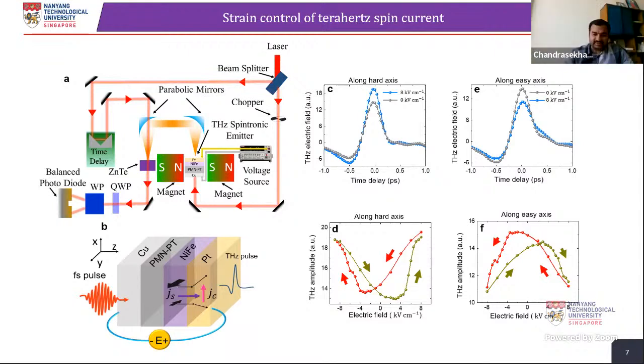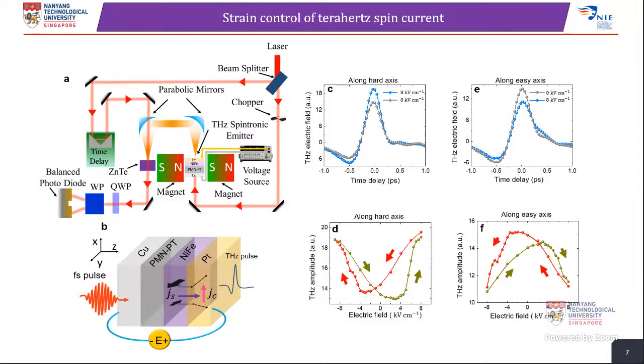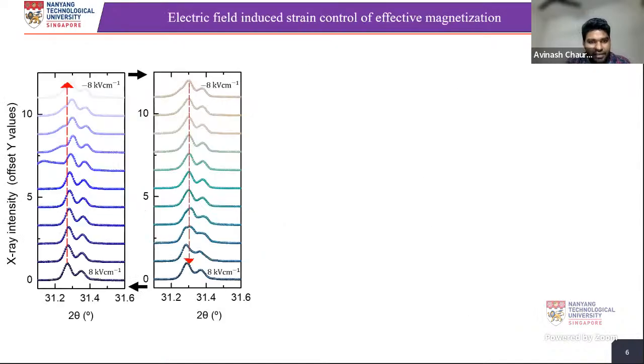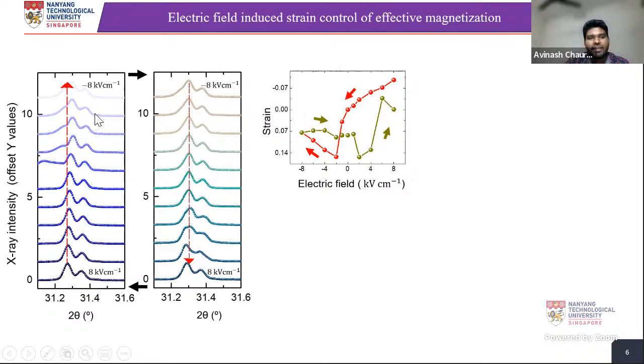That's a good question. Any other questions? Yes, Shaprit, last question. Hi, Avinash. How did you measure or quantify the strain in the nickel iron? First of all, we do not measure the strain on the NiFe; we measure the strain on the PMN-PT. This strain curve is for the ferroelectric layer, which affects the NiFe layer on top. NiFe is polycrystalline, but we are not measuring the strain on it. We apply the electric field on the PMN-PT layer, and it transfers the strain to the adjacent layer.